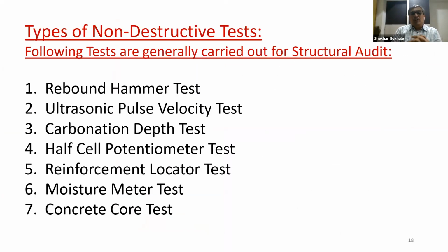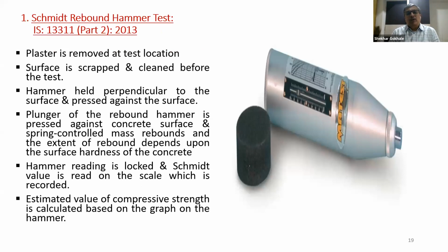Now the types of non-destructive tests we normally carry out. There are a number of non-destructive tests, but these are 7 tests which are commonly used. One is the rebound hammer test, which is called the Schmidt rebound hammer test. Second is the ultrasonic pulse velocity test, then the carbonation depth test, half cell potentiometer test, reinforcement locator test, moisture meter test, and concrete core test. I'll come to all these tests one by one.